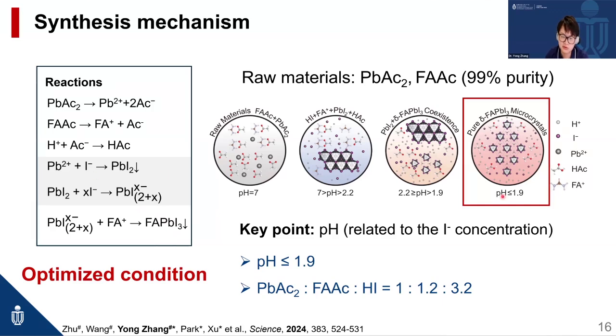So we tried to control the pH value to control the iodine ion concentration, and we found that a pH value lower than 1.9 is the optimized condition.